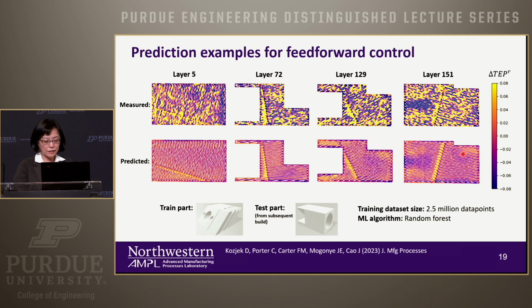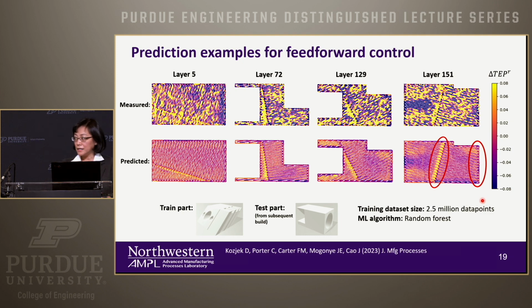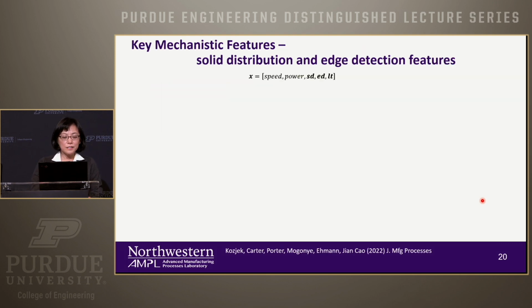Now, one thing that I want to call your attention to is this one. So here, for example, around the boundary, your laser is turning, okay? So you're turning the laser, and then you see the temperature profile. But also here in the middle, the laser is also turning, right? But the intensity is very different from the edge. Basically, this tells us you really need to take into account the material geometries, the part geometry, in addition to just the tool paths.